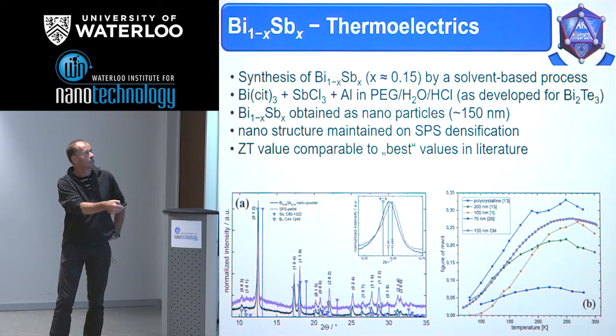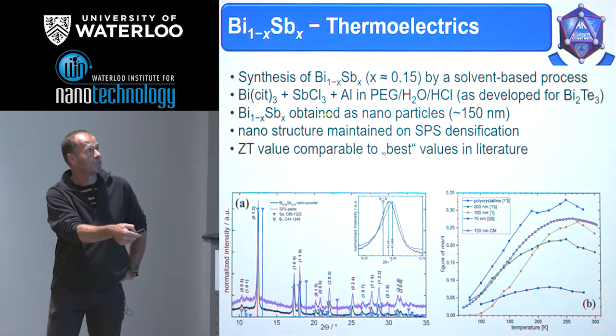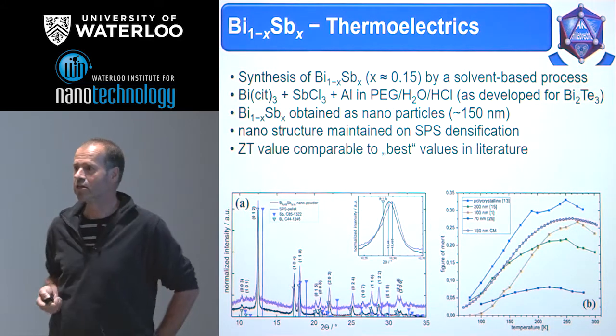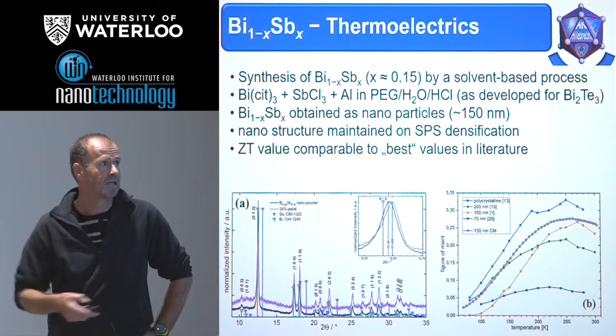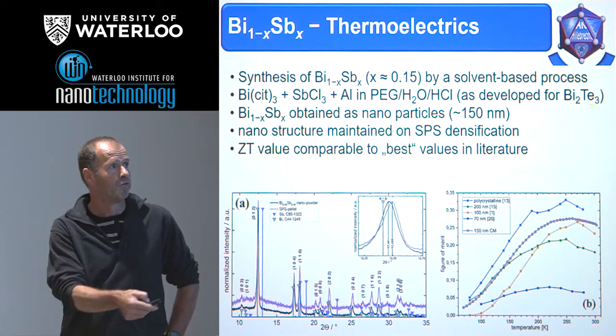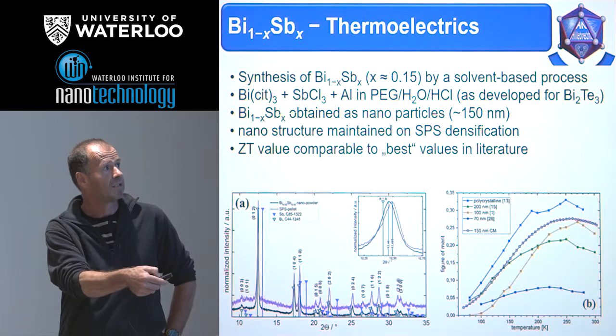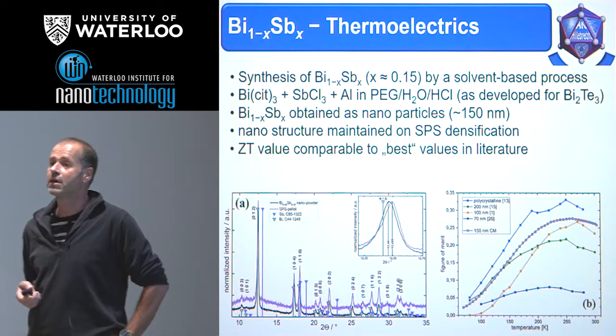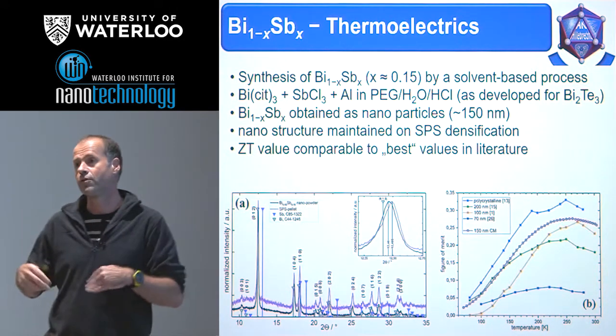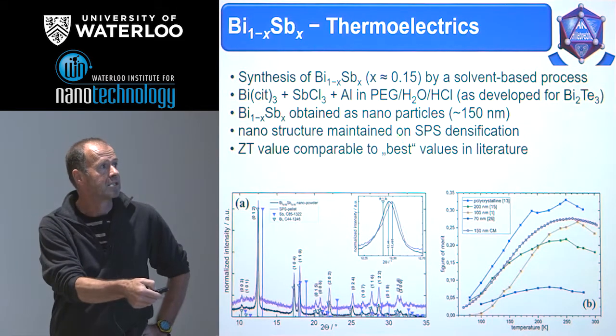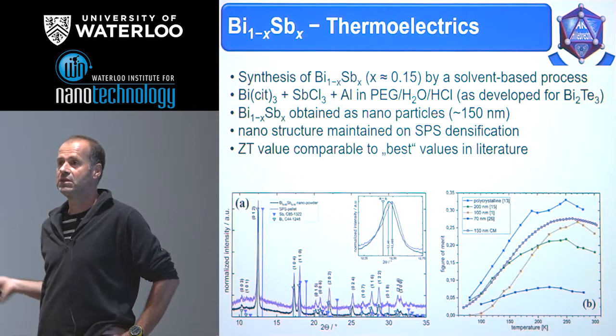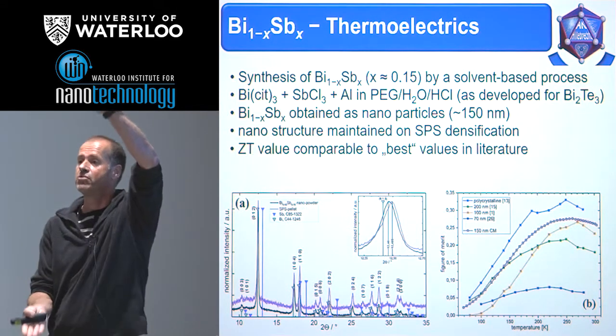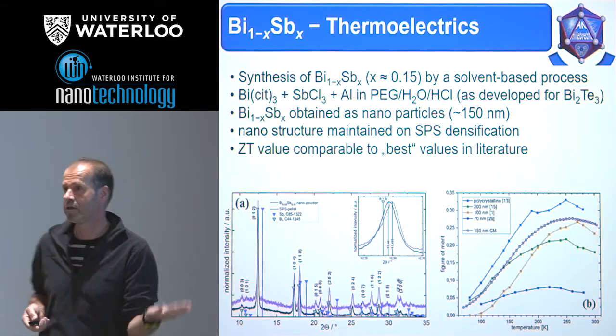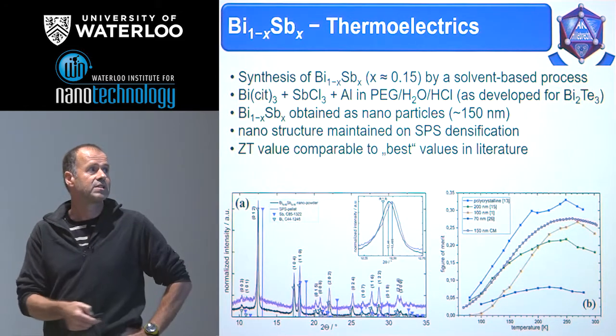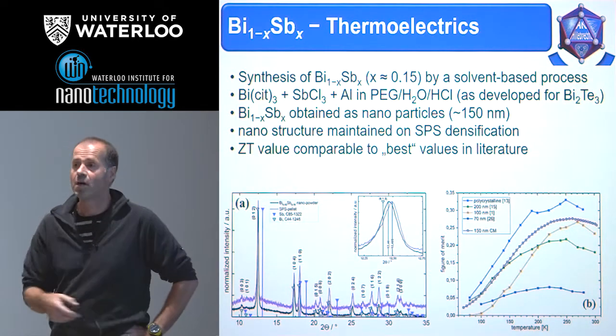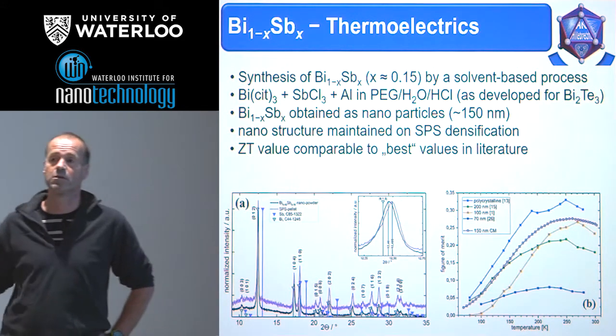And this is quite simple. We use the citrate of bismuth, the chloride of antimony, and reduce it with aluminum in a polyethylene glycol solvent with water and hydrochloric acid. This process we had developed, as already mentioned, for the bismuth telluride, and we were able to obtain well-defined nanoparticles, and we could show that we can produce a compact material for the thermoelectric application by the so-called spark plasma sintering technique. I'll explain it in more detail for the next topic, and that means that we can compress the system under applied pressure and temperature, and we could show that this process of densification keeps the nanostructure more or less unchanged. And that's important because of the thermal conductivity.